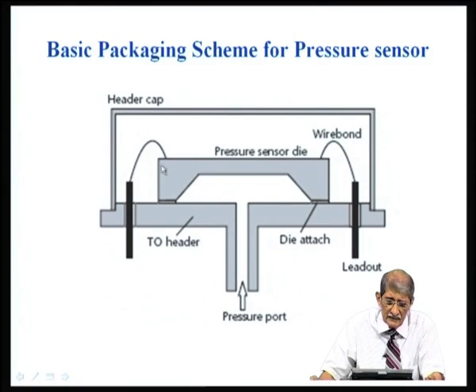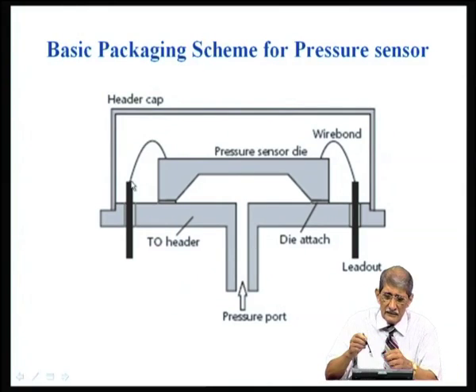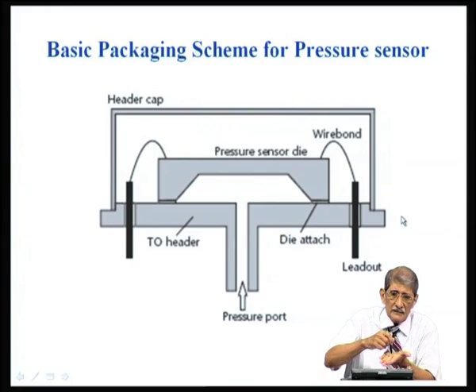So, there will be a pad on this region. You can bond wire onto this using a machine called the wire bonding machine. Take the other end of the wire, which is just about 25 microns, and bond onto this. You can do this by ultrasonic bonding. The ultrasonic bond is actually you have the wire bonded here, then taken to the other end here, you mount it on that point, and that will be vibrated like this.